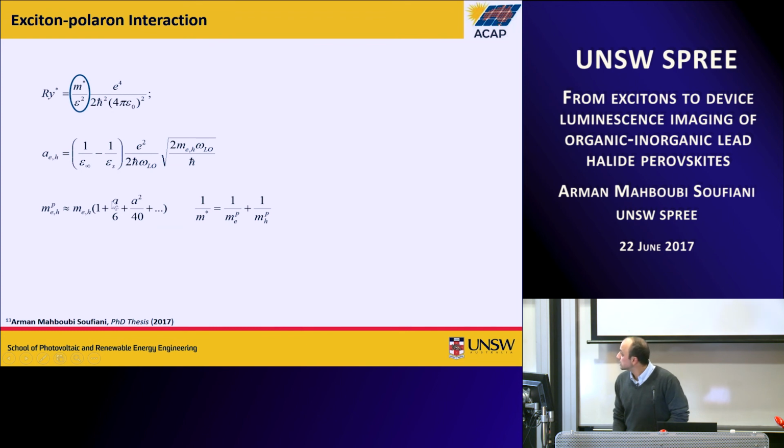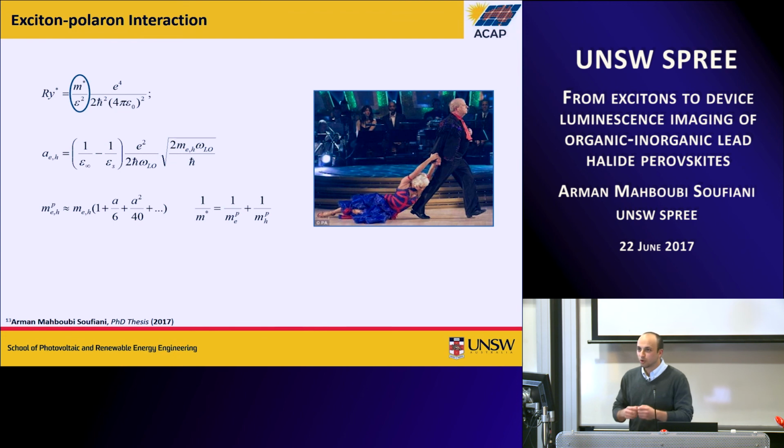And this is because of this coupling factor, which is inversely proportional to the square root of the phonon energy, right? So the polaron mass is larger than the rigid mass that you calculate from the electronic band structure of the semiconductors. And I just want to show you a picture so that you always remember what a polaron is: a free charge wants to move around in the lattice, but the phonons are grabbing the charge carrier and don't let it move.